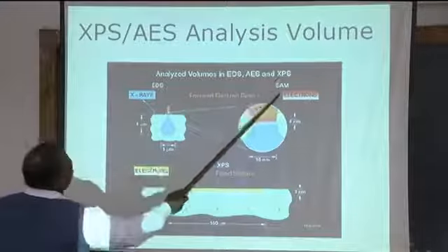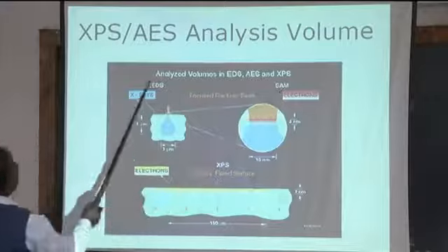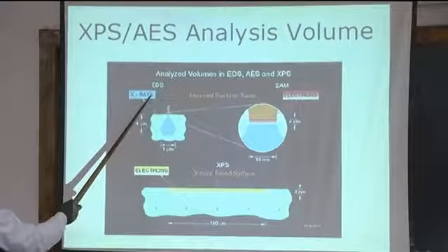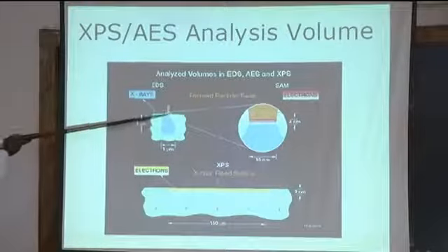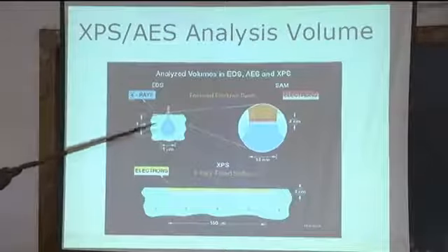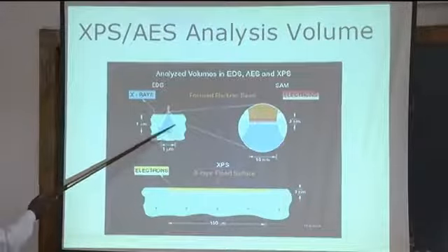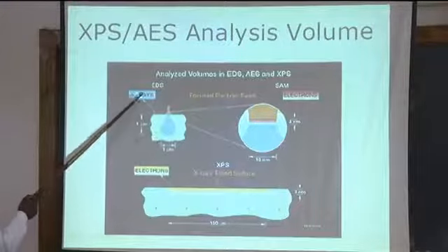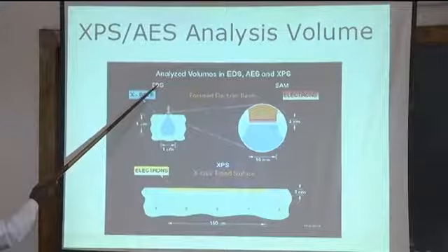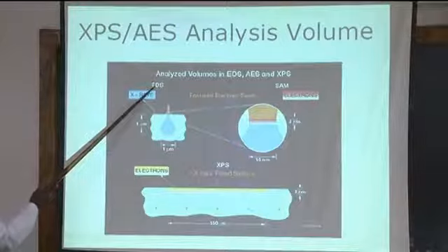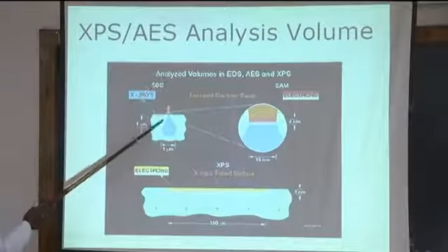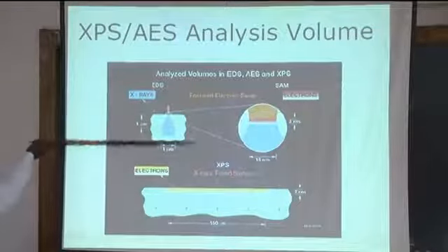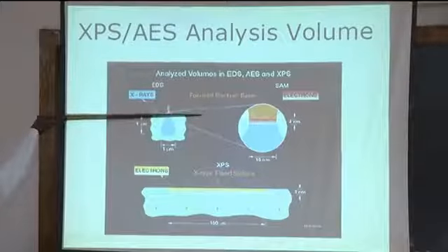I'll again put this just as a comparison. This is your scanning Auger, and this is your typical EDS in a SEM. If you see the area, 1 micrometer depth, 1 micrometer width, this is the interaction volume. So that's what it is for X-rays in an EDS or an EPMA in a SEM. In TEM, because this bulk is not there, once you make it thin, you can narrow down on that, going down to that capability I just mentioned.